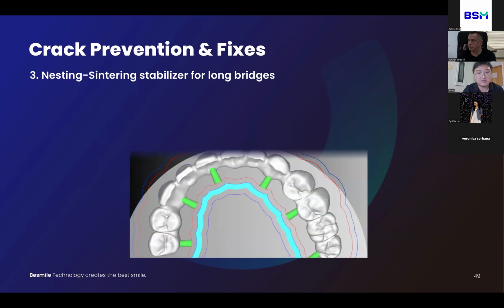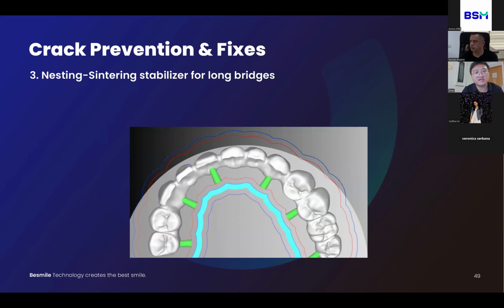Okay. And the third point is about the sintering stabilizer for the long bridges. For the long bridges, we recommend to add a sintering stabilizer when nesting. Otherwise, there will be a high risk of crack or, to say, uneven deformation. And we recommend to set this hollow sintering frame with 1.5 to 2 millimeters wall thickness. If you want to save material, you can mill a crown at the area in the middle of the sintering frame. You can mill one single crown.